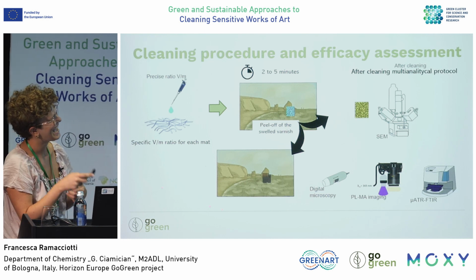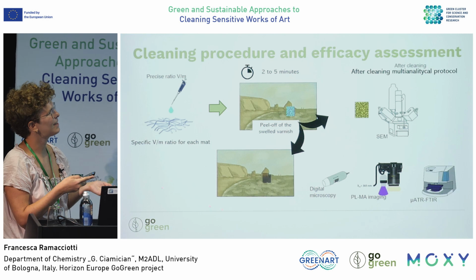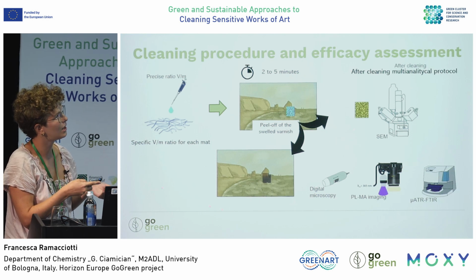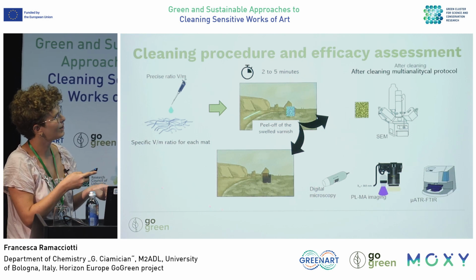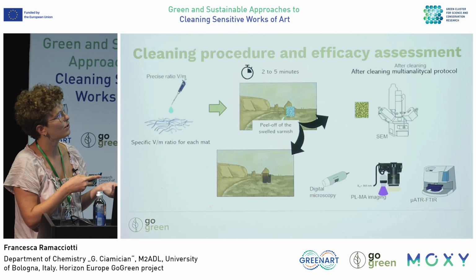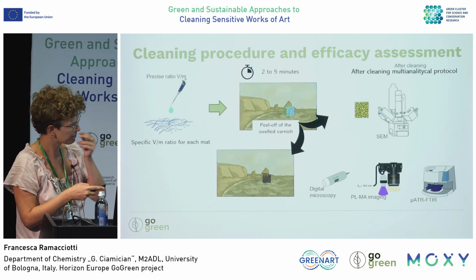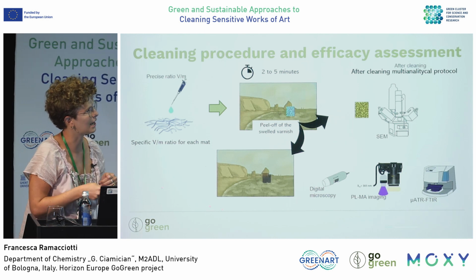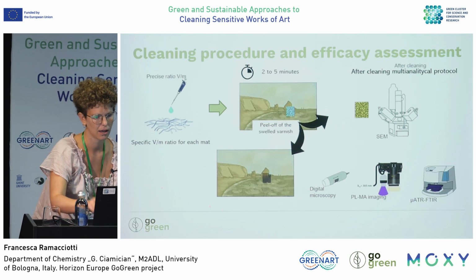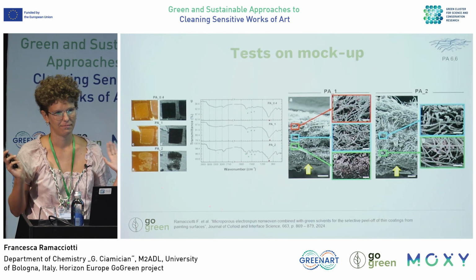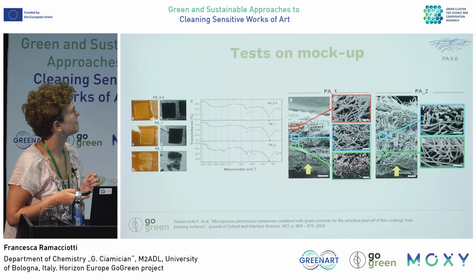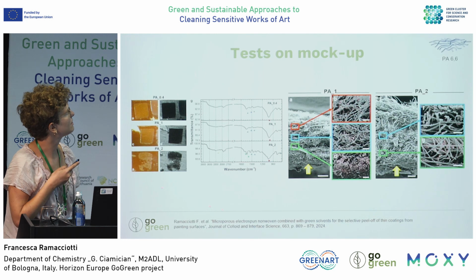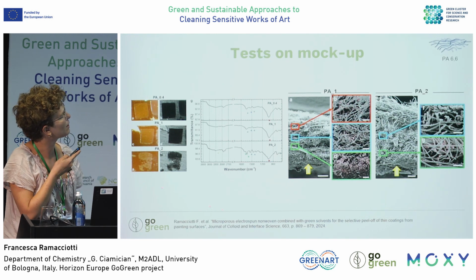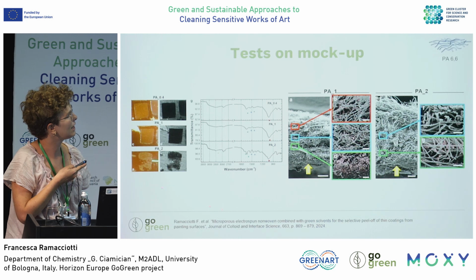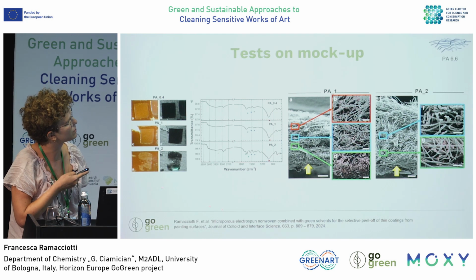of the varnish. Then, of course, we employed a multi-analytical protocol to study not only the efficacy, but also the mechanism. So we employed different imaging and spectroscopic techniques. We started testing our new materials on a mock-up, and we observed that when we increase the pore size and the fiber diameter, we have a decrease in the cleaning efficacy, so we have more residues.